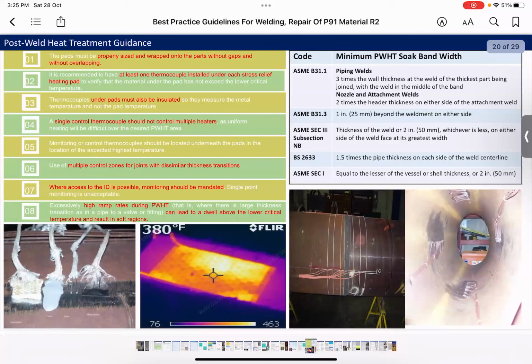And as you see here, the temperature gradient of the heating band, as shown in this IR image, we have different temperatures. So the thermocouple should be located under the highest expected temperature, and it should be insulated as shown here.